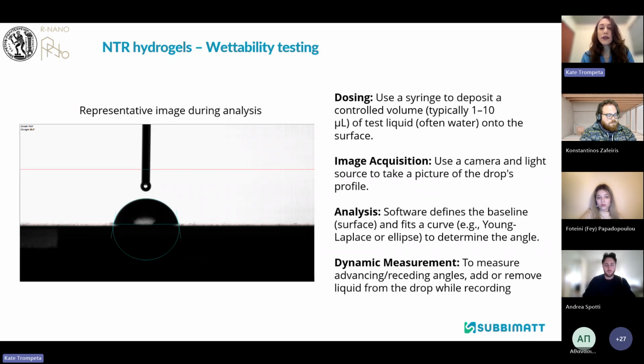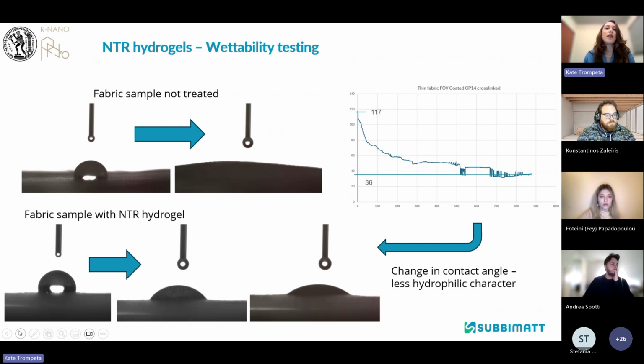In a dynamic measurement, we need to measure the advancing or receding angles and add or remove the liquid from the drop while recording. That's why in these cases we're taking a video and then try to make calculations during the whole procedure. So what we could see also in our case in SUBBIMATT. In the first case, when we have a fabric sample that's not treated, you see that we can have a drop at 0 point, and after a while, the water is totally absorbed, so we cannot observe the drop anymore.